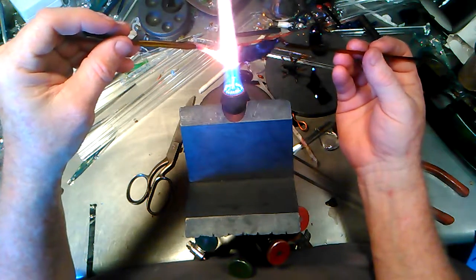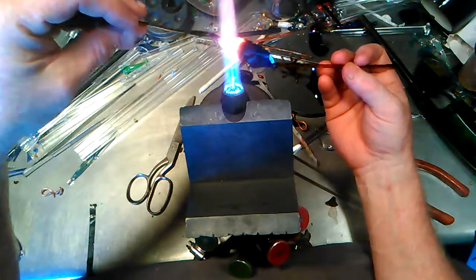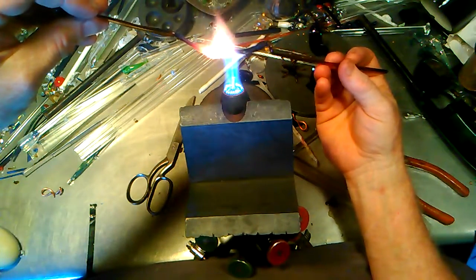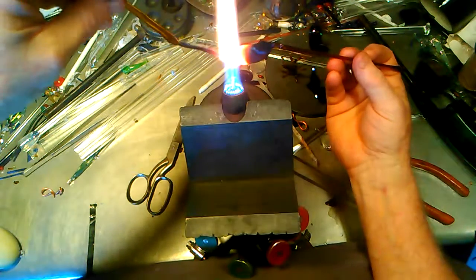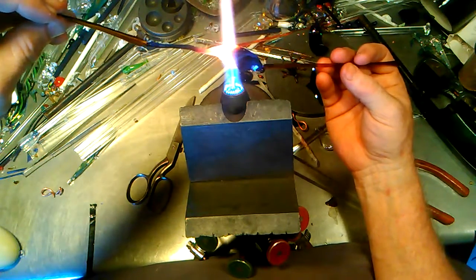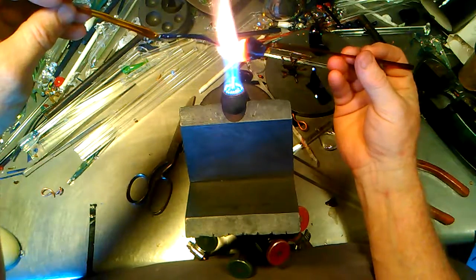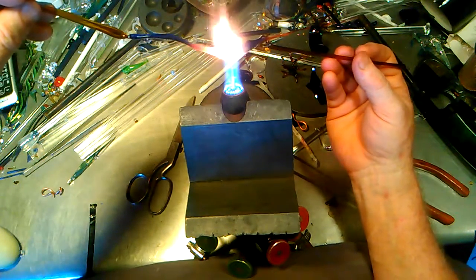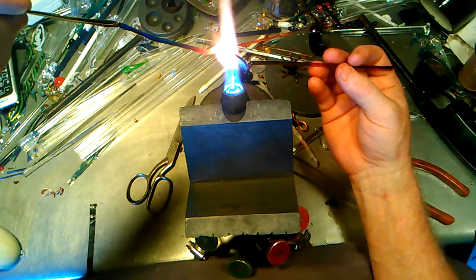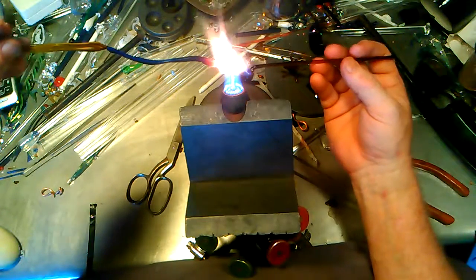Right now, I'm going to stretch this out and make some rods. Okay. We're moving on in. And it's flowing quite nicely. And I'm trying to do this very slowly and methodically. Usually, if I do this with Boro, I'd have flattened it out and twisted it up and gotten it going already. But with soft glass, the more bubbles that you flatten out and twist in causes more stress on the softer glass side. Okay. And yes, this is not coming out as straight as I want it at the moment. But it will do the job. I'm only going to be making little things out of it.